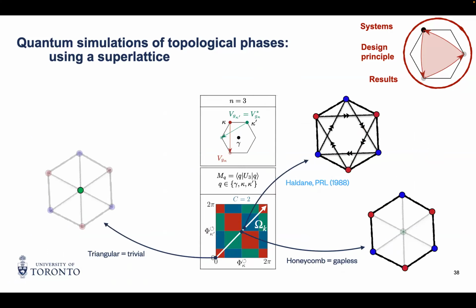So yeah, I can give you one example. Let's say I apply a superlattice potential that is triangular, that has C3 symmetry. Then I can start either from a triangular superlattice potential, and let's say I don't have any Berry curvature, and this is in the trivial region. If I start from a honeycomb potential, I start at pi here, and my system is gapless, so that's the Dirac cone of the honeycomb lattice. And you have to trust me on that, but as I increase the Berry curvature in my system, I move along the first diagonal of that plot.